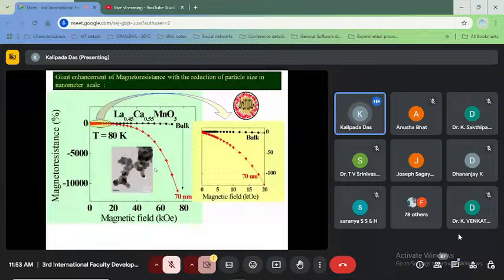So this is a graphical abstract type picture. All the phenomena are given here. In the case of the antiferromagnetic nanoparticle, if we reduce the particle size, the magnetoresistance gets enhanced. Not only at high field, but it is also still present in the lower magnetic field region. So an enlarged picture is given here, and this phenomenon can be analyzed by using the core-shell type nanostructure configuration due to the magnetic phase separation.